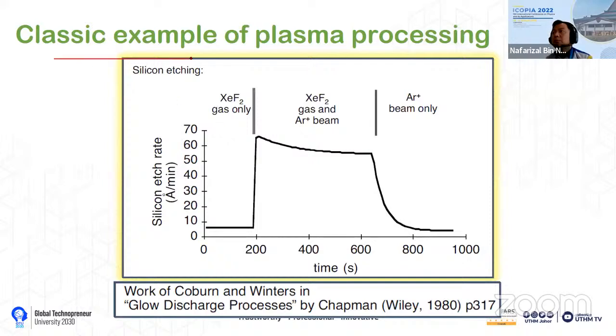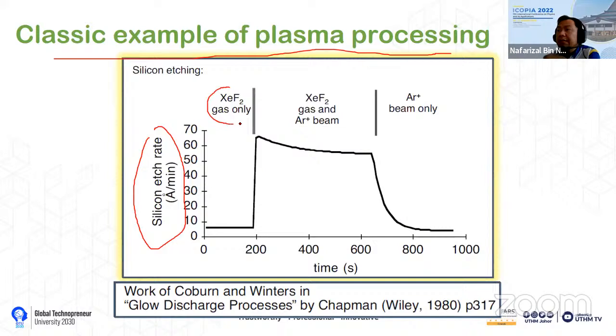Here is a classic example of how important plasma processing is. This is an example of the silicon etching rate, the removal of silicon, if we use a gas only or if we use a gas with a plasma. If you use a gas only to do the silicon etching, we need a fluorine-based gas, so they use XeF2 here. We can see that with gas only, the etching rate is below 10 Angstrom per minute. Very, very low. You cannot do the etching fast.